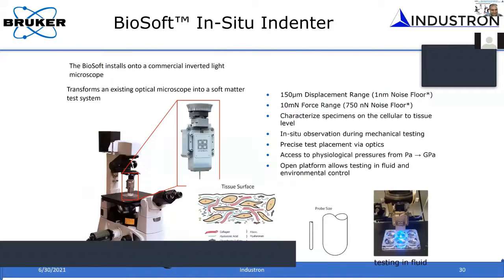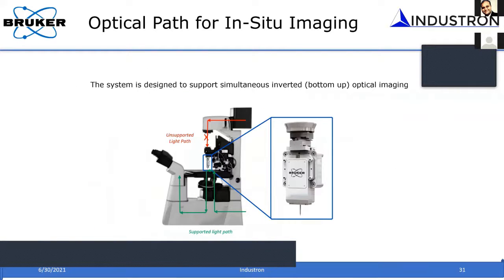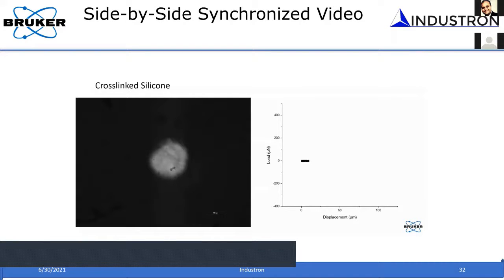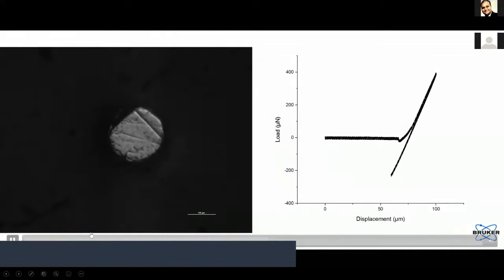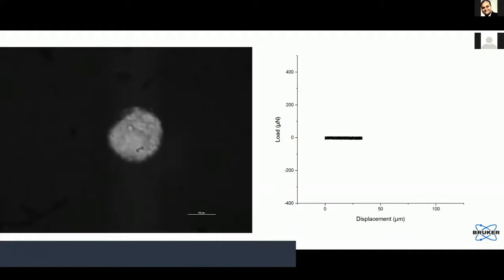So with that, we were able to put that on a biological microscope without affecting the light path. Now, this is an inverted biological microscope. When you use this, we can apply this transducer to apply force, but at the same time you can also observe through this optical microscope, as you bring the probe in contact with the sample surface, how the contact is evolving. This is just a simple video where you can see the load displacement curve on the right, and on the left you can see how the probe is making contact. This is done very fast, so you're not able to see how the contact is changing, but you have the ability to observe that through the optical microscope, and the video is also synchronized with the force displacement curve that you measure.